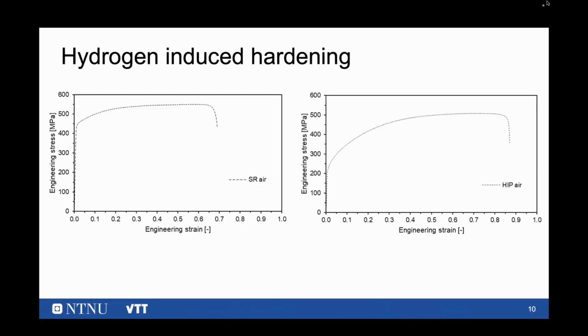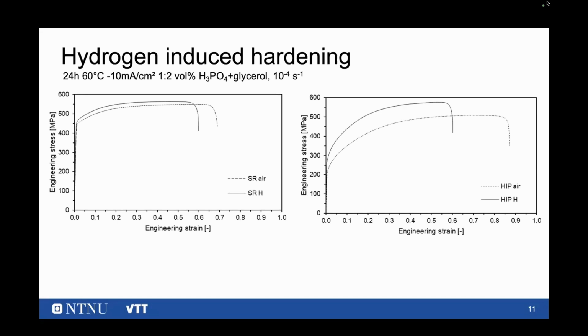The mechanical curves reflect what we saw earlier, but first I want to point out the difference between the air stress relieved and the hot isostatic pressed condition, because the stress relieved condition has a higher strength and also a lower elongation at fracture, but still it is quite ductile for both conditions. So when we then add the hydrogen condition, we see something interesting. Well, hydrogen embrittles the material, but to a lower extent in the stress relieved condition: only 13% in the stress relieved condition and 31% in the hot isostatic pressed condition.